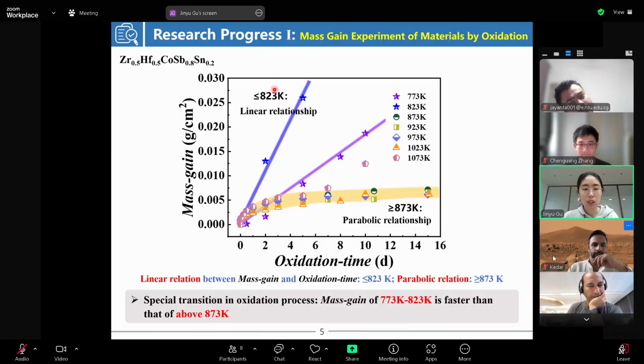This work takes this component as an example, starting with the oxidation mass gain experiment. The materials were found to undergo a special oxidation process transformation. The mass gain is linearly related to the oxidation time at lower temperatures, while it follows a parabolic relationship at higher temperatures. This special transformation leads to a fast and uncontrollable oxidation rate in a low temperature range. Then we carried out morphology characterization to understand the oxidation mechanism.